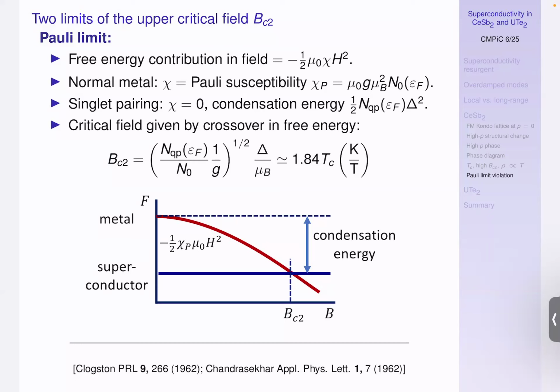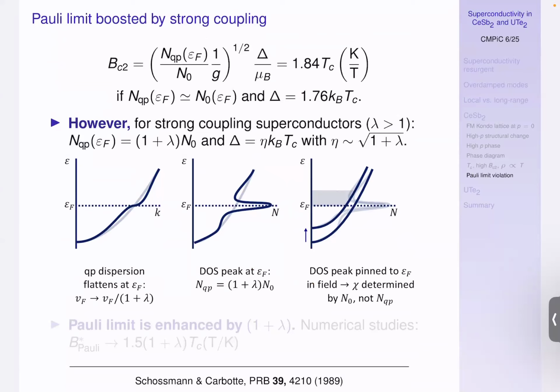But when you look closely, it's not that easy, because it's only independent of the density of states, which comes up in both of these, because both densities of states are usually taken to be equal, but then fundamentally not equal. One is the density of states that dictates superconducting properties, and the other one is the one that dictates magnetic properties. And there's a relatively subtle argument, maybe if you ask the questions, I can return to later, for saying that the magnetic susceptibility really doesn't see the full quasi-particle density of states, which in a phonon-mediated superconductor always peaks at the Fermi energy. It sees the underlying band density of states. So the two susceptibilities may differ by a factor of 1 plus lambda.